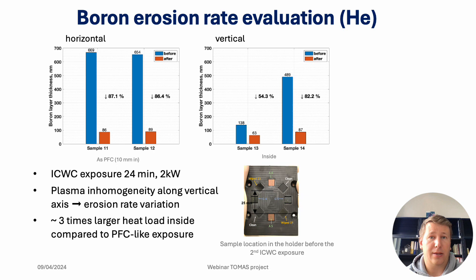These results validate the numerical modeling of erosion based on the plasma parameters. It's interesting to see here that the erosion was homogeneous in the case of horizontal exposure. We can see the deviation of erosion rates with respect to the sample location for the vertical exposure, which is due to inhomogeneous plasma profile along the vertical axis.